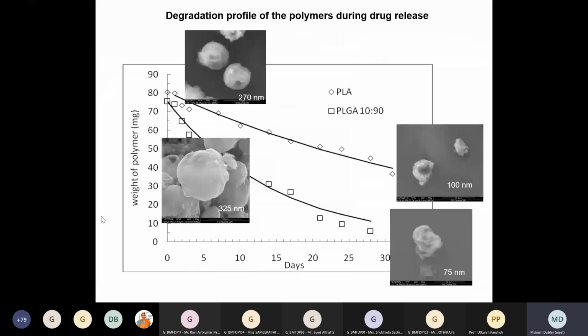We loaded it with the drug meropenem and then looked at how it degrades over a period of 30 days. This is polylactic acid, which means there is no glycolic at all, the top graph. In 30 days you can see the polymer weight falls from 80 milligrams to about 50 milligrams. Whereas with polylactic-co-glycolic acid, where we have more glycolic, almost 90% by weight to 10% lactic acid, it degrades to almost 10 milligrams. So almost 90% of its original weight is lost within 30 days. When you have more lactic acid, the biodegradation of the polymer is much less. When we have more glycolic acid, we can achieve very good degradation.